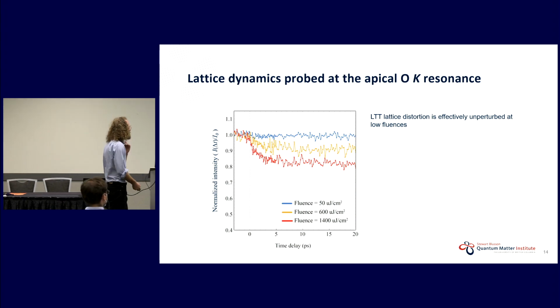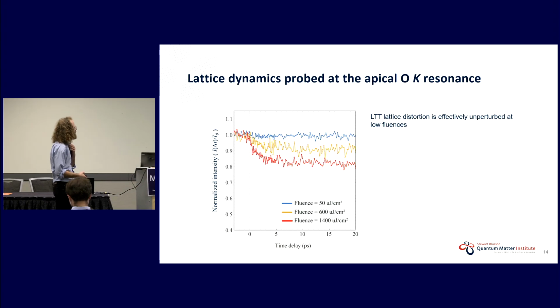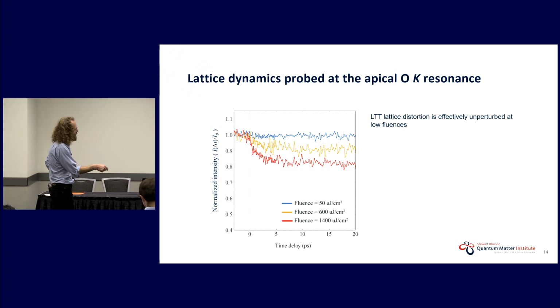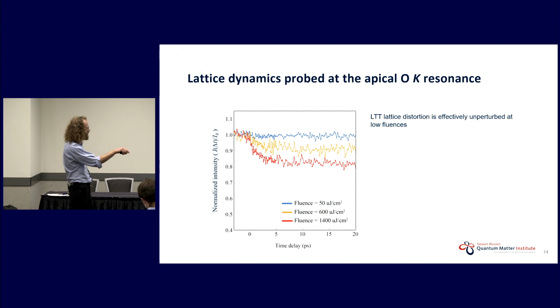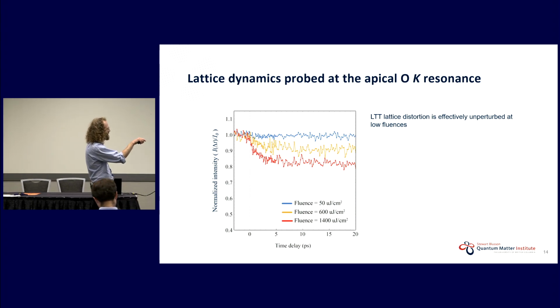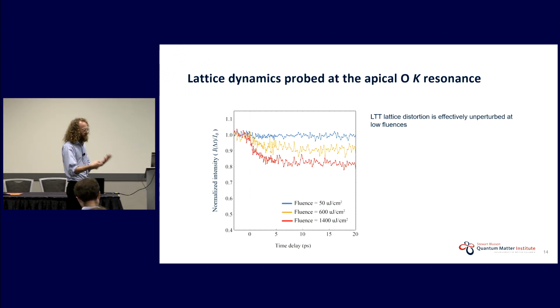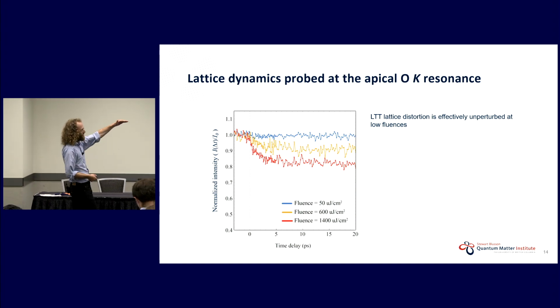No, that's right, yeah. Oh, I'm jumping ahead. So then I want to say, okay, now let's reduce the fluence. If we get down below 100 microjoules per square centimeter, we get into a regime in which the lattice is essentially unperturbed. We don't see a strong perturbation of the lattice. So we say that's now where we're going to work.